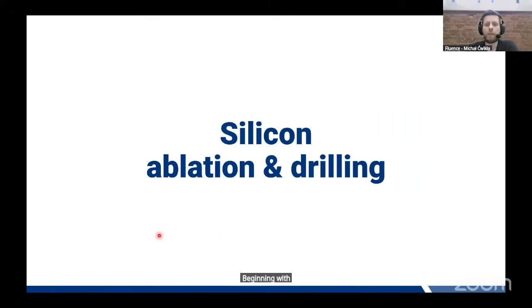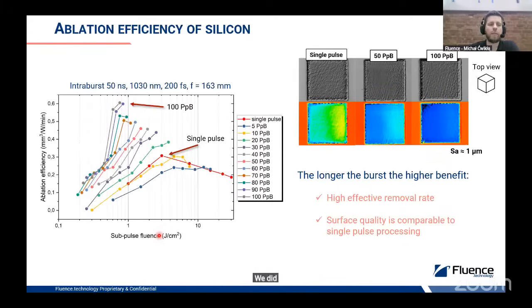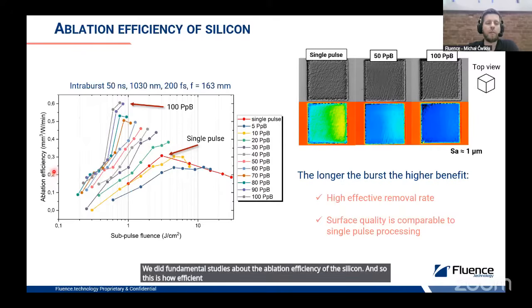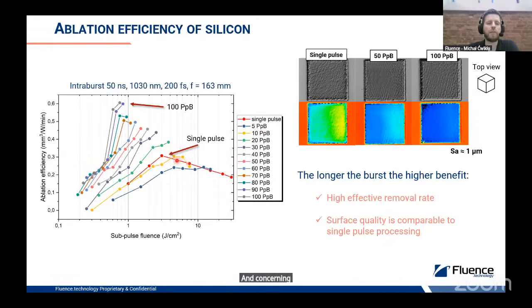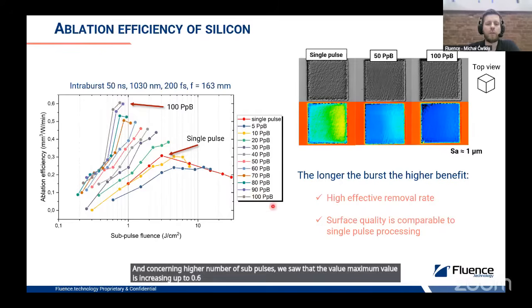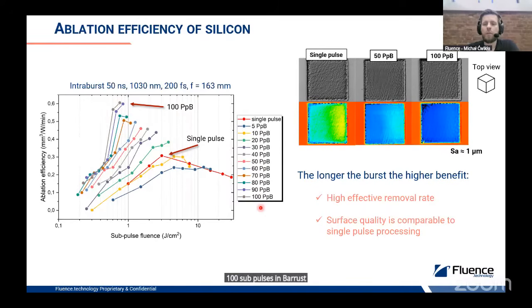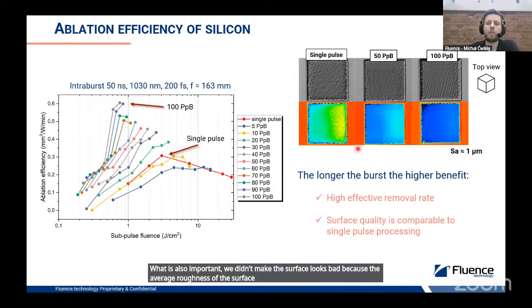Beginning with silicon results, we did fundamental studies about the ablation efficiency of silicon, so this is how efficiently material is removed with respect to applied energy. For single pulse operation, we managed to reach up to 0.3, and with a higher number of sub-pulses, we saw that the maximum value increases up to 0.6 for 100 sub-pulses in burst. What is also important, we didn't make the surface look bad, because the average roughness of the surface was comparable to single pulse operation, and we also didn't notice a strong redeposition or heat affected zone in this regime.